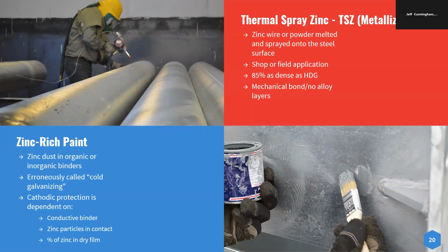Zinc thermal spray and metallizing is zinc wire or powder that's melted and then sprayed onto the steel surface. It's 85% as dense as hot dip galvanizing and is a mechanical bond. There are no alloy layers. You don't get that metallurgical bond.